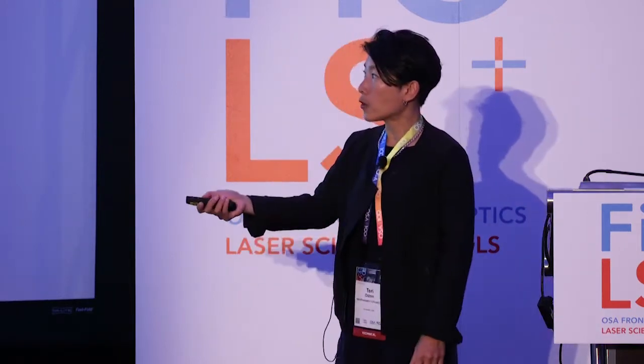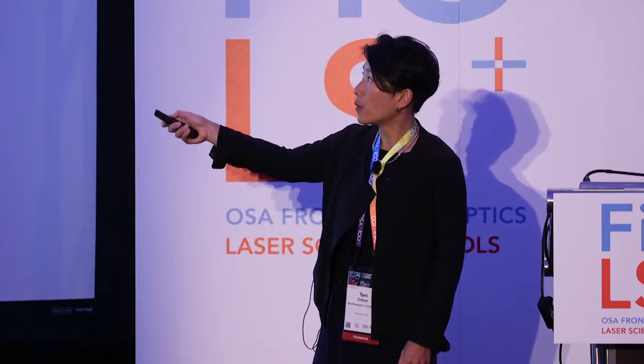Okay, in terms of structure, we can also do something which I think is really neat, which my group likes to think about, is these hierarchical length scales of interactions. And so this is the single lattice that I showed you earlier, where you have a single particle and they're all organized with the same spacing. But what you can also do is you can make what we call super lattices. So you have this length scale stays the same, so the separation and the particle sizes of the smallest length scales are the same, but we can organize them into what we call patches. And so now you have arrays of arrays. And so I think the best language that we can think about these are super lattices.